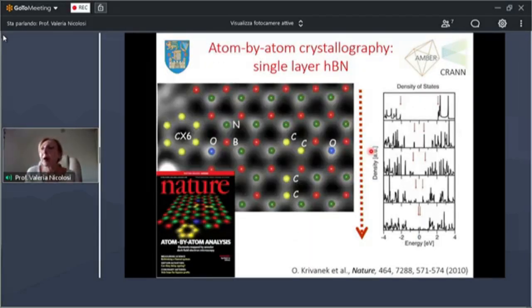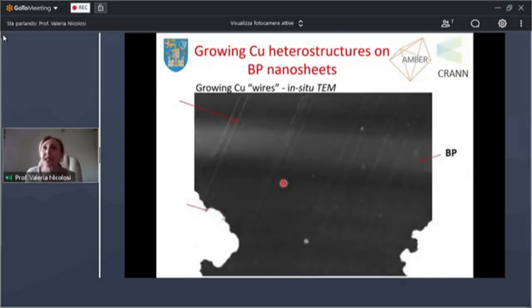In this other work that we published in Nature, and we got the cover in 2010, for example, was on boron nitride. And we discovered that boron nitride was easily doped by liquid phase exfoliation, in fact, with carbon and oxygen type of inclusions. We learned that carbon doublets were always replacing boron and nitrogen pairs, and oxygen inclusions were always substituting nitrogen. Importantly, what we learned was that we could indeed tune the band gap of the material from a wide band gap semiconductor or even insulating material like boron nitride into a semiconducting material with a much smaller band gap, simply by doping it with higher quantities of carbon. So these are all very important things that we learned.